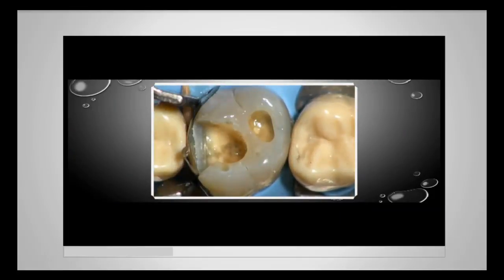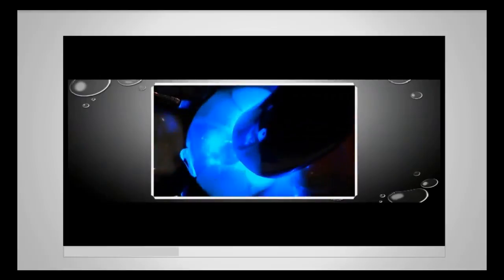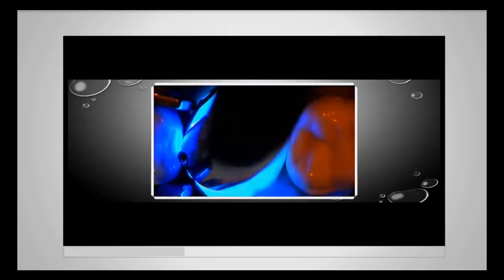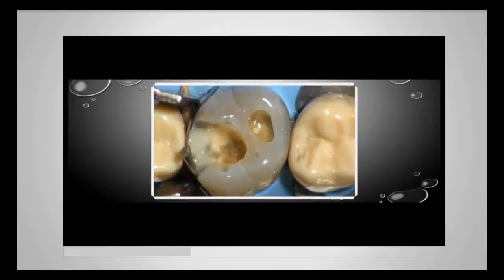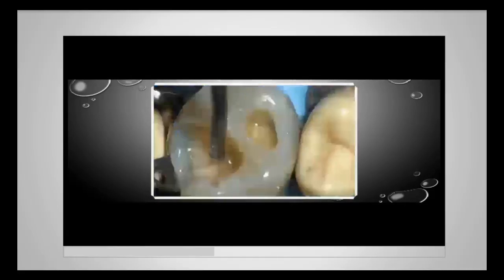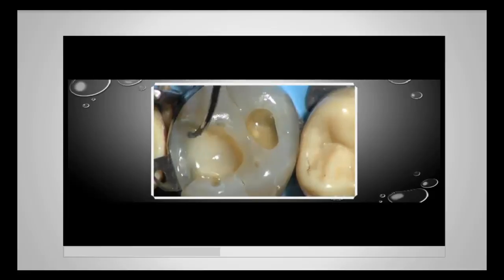Now I'm going to come in with the flowable. The first layer is going to be at the matrix margin right there. We're going to put that in. We're going to cure that. You'll see quick. Now we're going to come in and add the rest of the flowable covering all the dentin. Now we're going to cure that. We're going to come in with the next layer, put in a little more flowable in this case, another millimeter.